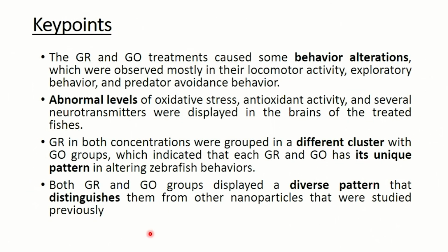Overall, the present study has several key points. First, the graphene and graphene oxide treatments caused some behavioral alterations which were observed mostly in locomotion activity, exploratory behavior, and predator avoidance behavior. Second, abnormal levels of oxidative stress, antioxidant activity, and several neurotransmitters were on display in the brains of the treated fish. Next, graphene in both concentrations was grouped in a different cluster from the graphene oxide groups, which indicated that graphene and graphene oxide each have a unique pattern in altering zebrafish behaviors. Last, both graphene and graphene oxide groups display diverse patterns that distinguish them from other nanoparticles that were studied previously.